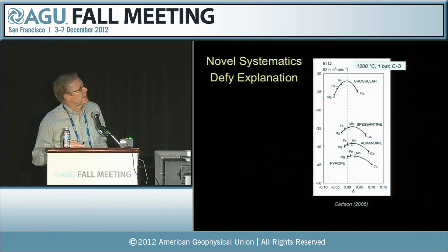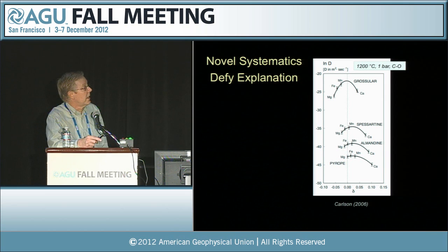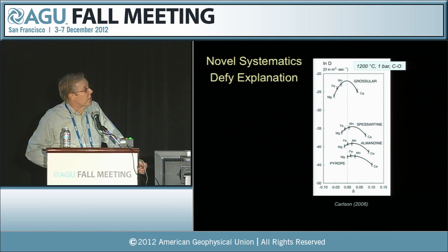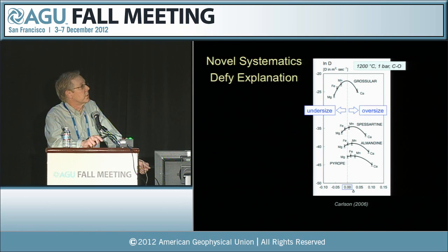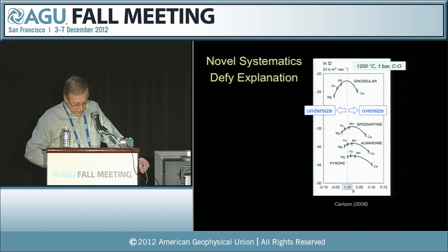On the vertical axis is the logarithm of the diffusion coefficient, natural log, and on the horizontal axis we have a measure of ionic radius. Now this quantity here, delta, on the horizontal axis is actually a misfit parameter. So delta has the value of 0 for an ion that has a radius which, when added to the radius of an oxygen ion, sums up to exactly the bond length in the particular site that that ion sits in. And so oversized ions have values that are positive and undersized ions have values that are negative.